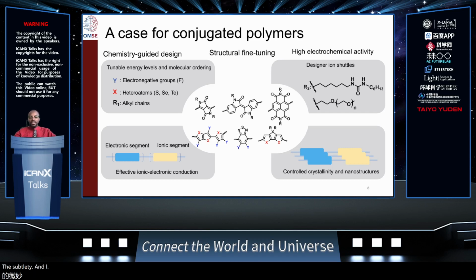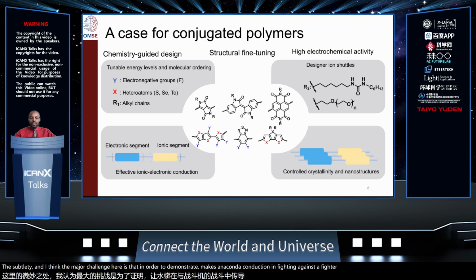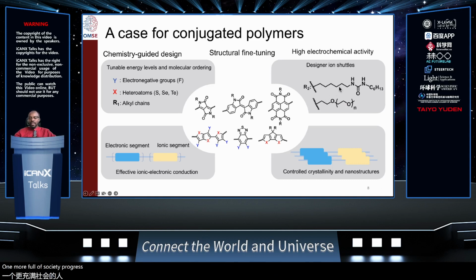And I think the major challenge here is that in order to demonstrate mixed ionic electronic conduction, you're fighting between two different modes of operation. For ionic conduction, we actually want an open structure, where we want more polar side chains, for example, that can allow for ions to go in. While for electronic conduction, you actually want more compact, so highly crystalline structures where electrons can delocalize very easily.